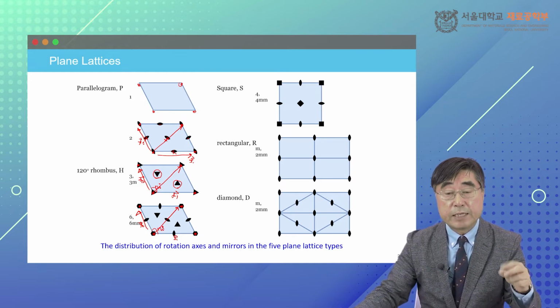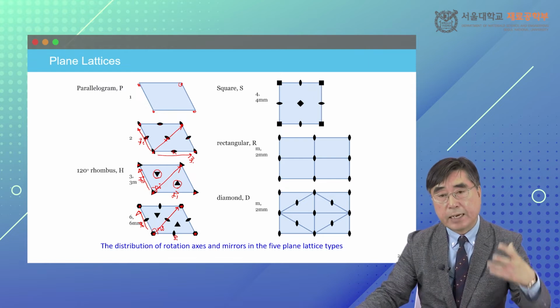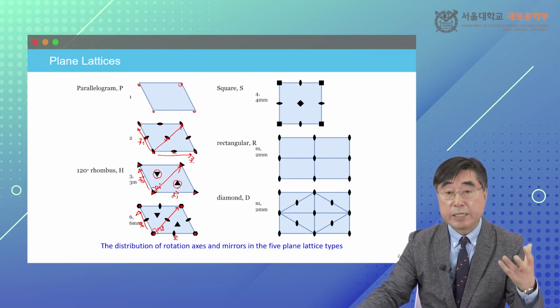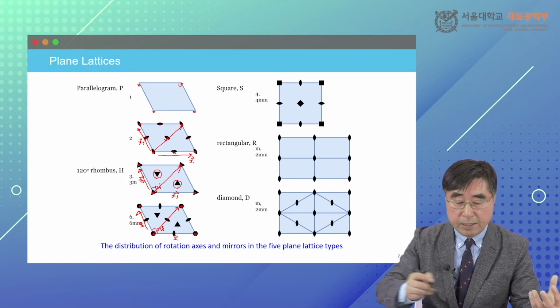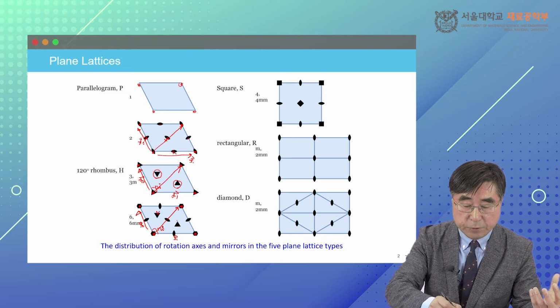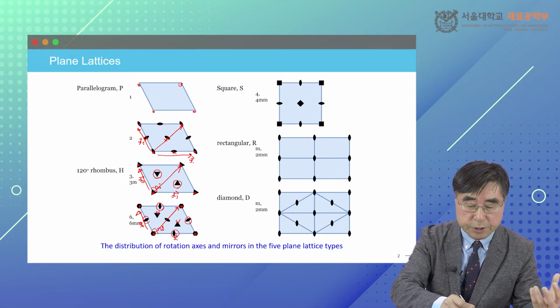Now, the lattice point has six-fold symmetry, and I explained to you that when the lattice point has one six-fold symmetry, and a perpendicular translation vector is involved, then threefold symmetry is developed at these positions, and along the bisector lines, two-fold symmetry is developed at these positions.